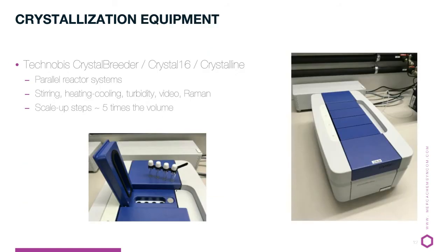The crystallization systems we use for the initial experiments, as well as for the optimization of a selected form, are the Technobis parallel reactor equipment. We have a Crystal Breeder, Crystal16, and a Crystalline. The only difference here is the size, the working volume, and the scale-up steps are about 5 times that volume. All of them are parallel reactor systems, and they are applied with stirring, heating, cooling, and turbidity. For the larger system, there is also video and the possibility to measure Raman.